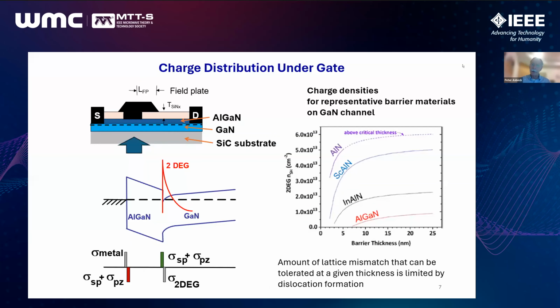The situation is clearer if we look at the band diagram. I cut through the structure normal through the gate and channel, and the results are shown here. At the interface, in barrier and channel, there's a significant positive polarization charge. And this is compensated by a 2D electron gas that forms at that interface. Interesting and important to notice also that there's a corresponding polarization charge that's negative that forms at the surface of the AlGaN, essentially equal to that earlier interface. This is compensated in turn by a positive charge associated with a depletion of the electrons in the metal over a very short distance.